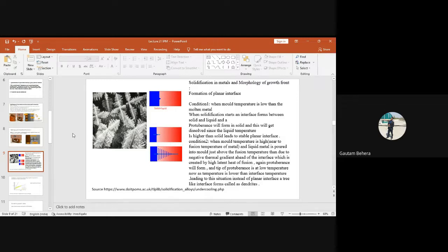Technically, the concept is called homogenization annealing, or some people call it homogenization only. High temperature homogenization. But this will take a lot of time, maybe 10 hours, 20 hours. That means you have to keep the ingot inside the furnace for 10 hours, 20 hours, 30 hours, depending upon the cross sectional area, right? Because diffusion also takes time. It is not so fast a process. But the higher the temperature, the higher the rate of diffusion. You have to remember.